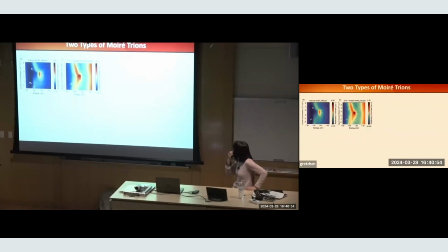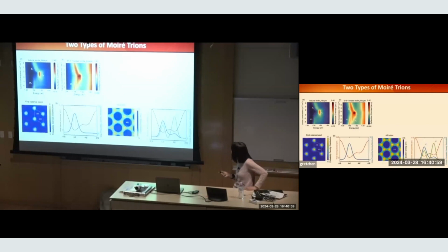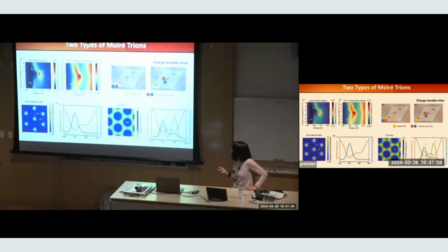And then I talked about the trion, which is a bound electron-hole pair. I'll skip the detail and just show you the special configuration where the electron-hole pair may not be sitting at the same location as the doped charge. So you can have this special situation. You can control the separation between the doped hole and the electron-hole pair, or between the electron and hole within the exciton.